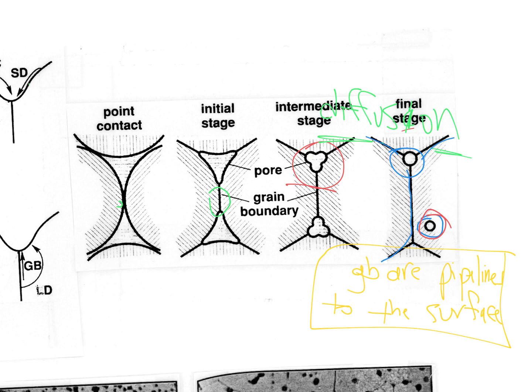All right, so then we have the worst kind of diffusion for us, which is volumetric diffusion, or lattice diffusion, as it was defined in those tables, meaning that it has to exchange a vacancy or a nitrogen ion or an oxygen ion with a neighboring atom, and those two kind of do the little dance, and eventually it gets to the grain boundary, and then it can diffuse to the surface more easily.